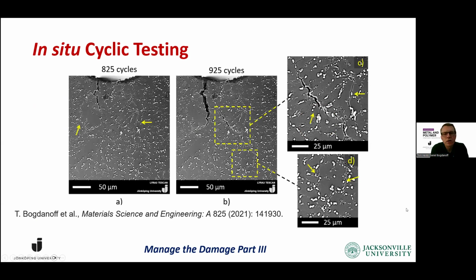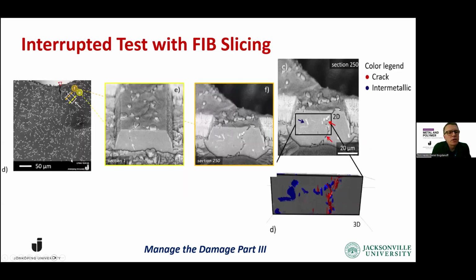If you take the next slide, we decided to take one area in front of the propagating crack and see how the material looks in front of the propagating area. You can take the next slide more. So we decided to interrupt the test that we see in figure D here. Then we used focused ion beam milling to take out the area in front, so we can create a 3-dimensional volume. And then using software, we can highlight all the cracks in the material with red color and all the intermetallics in blue. So this is an area of 250 slices, so we can see what is happening.